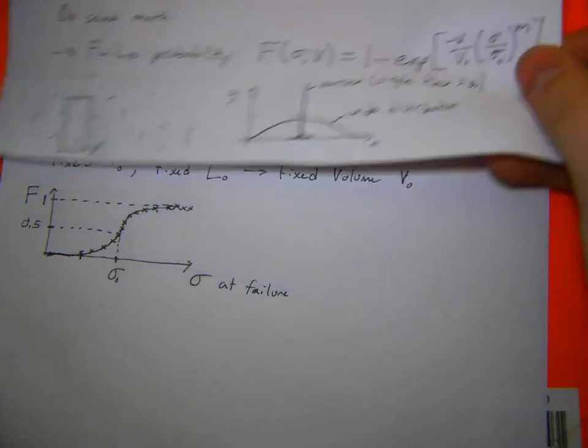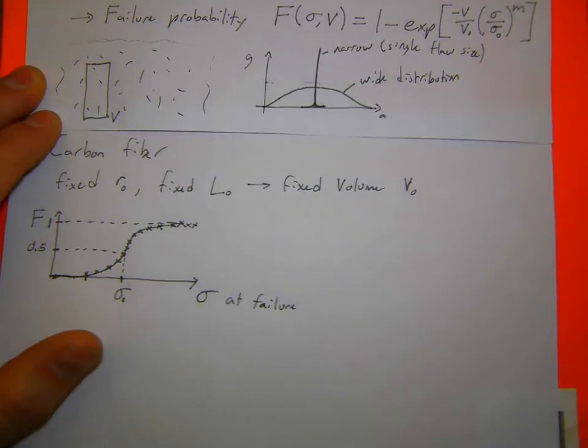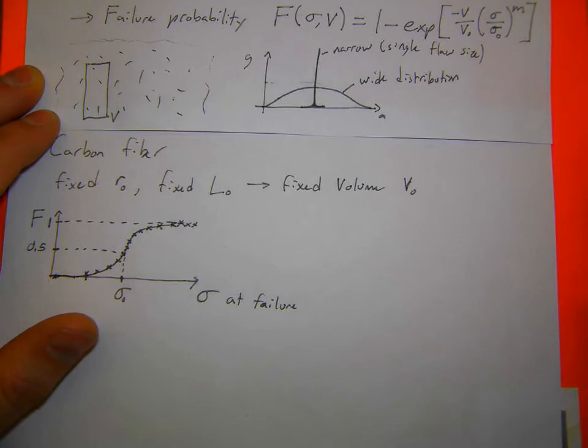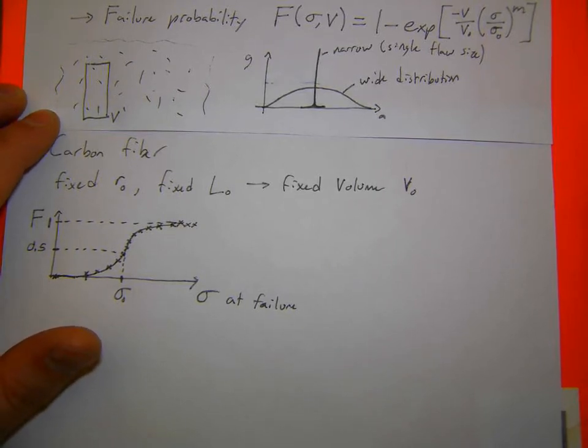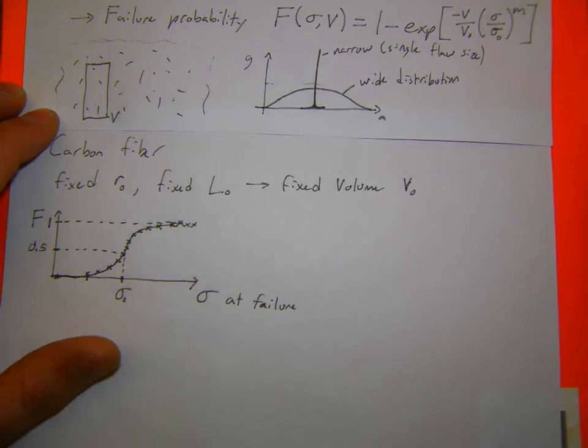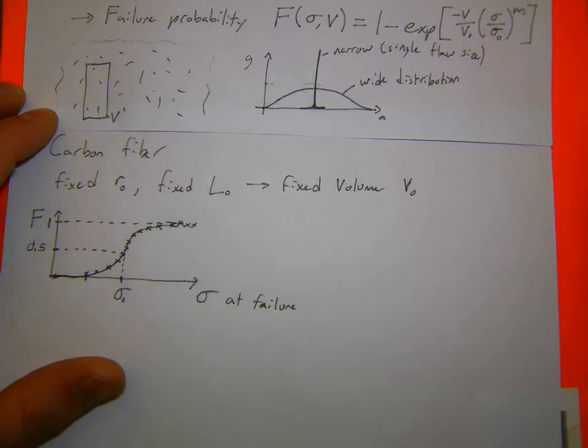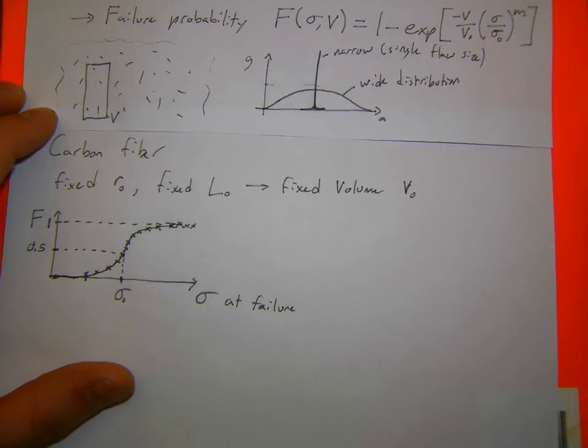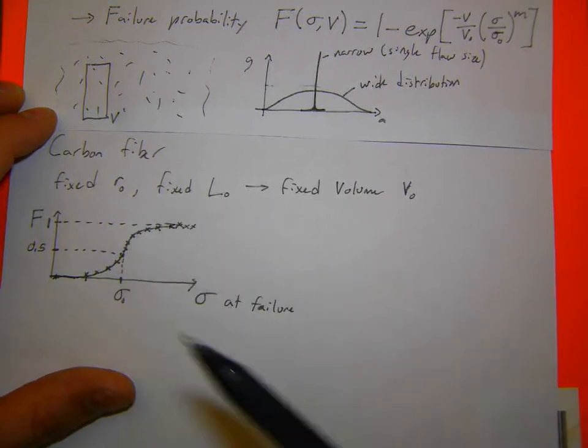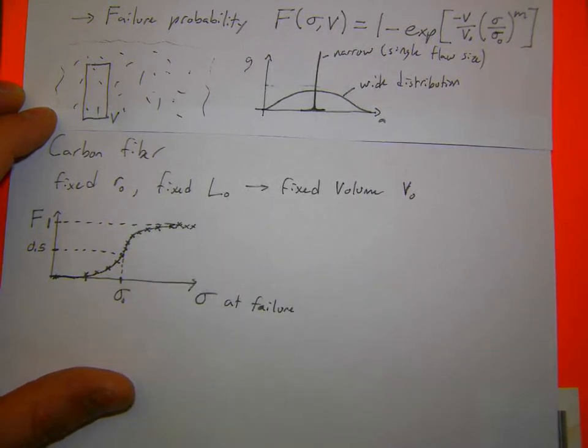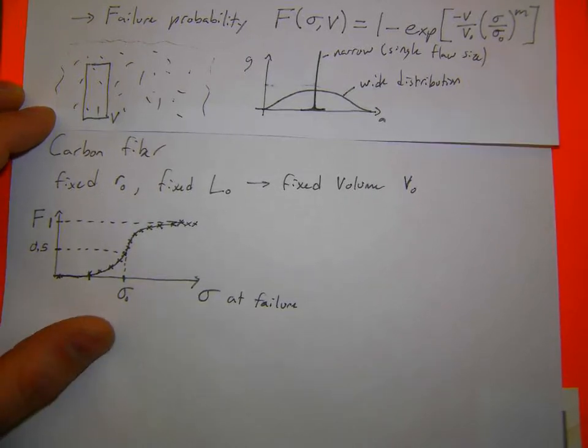If half of the fibers fail, doesn't that increase the stress in the remaining fibers, because then it's a smaller cross-sectional area? For the carbon fiber composite, yes, it does. But that's something you've all seen now. In practice, you would be taking individual fibers and pulling them until they break. So this would be like individual fiber tests, and you would get like 20 trials of this single fiber. And the more trials you do, the better distribution you'll get, because you'll have more data for what stresses they break at.